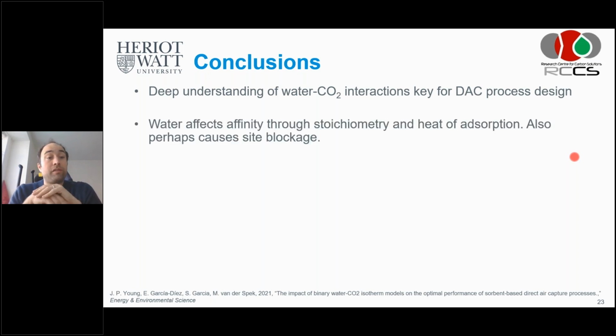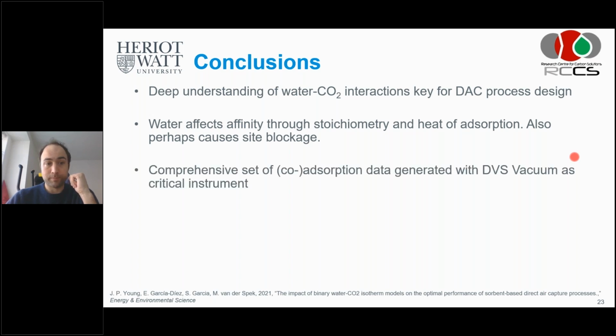We know that water affects the affinity through stoichiometry and heat of adsorption. So basically, the CO2 isotherm in wet conditions becomes steeper at the origin, in the Henry regime. So it affects the affinity, and that is really important and really helpful for direct air capture. And also perhaps causes site blockage. That's still a question mark, but we hypothesize that that's the case.